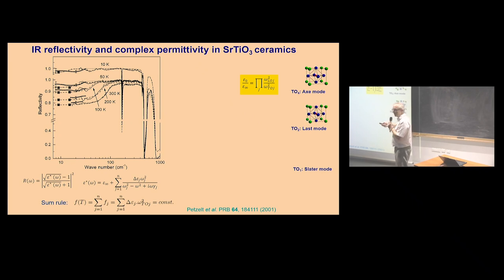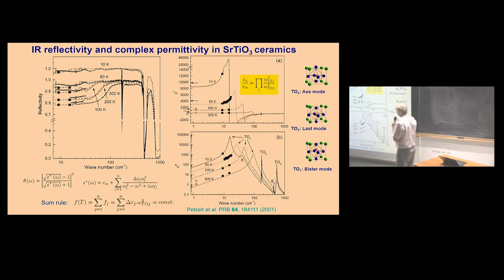But if you combine it with infrared and terahertz data, which we have here, we can explain such phonon softening, and there is such a lowest frequency phonon, shown moving on a logarithmic scale. And this softening is finally responsible for the huge increase of permittivity.